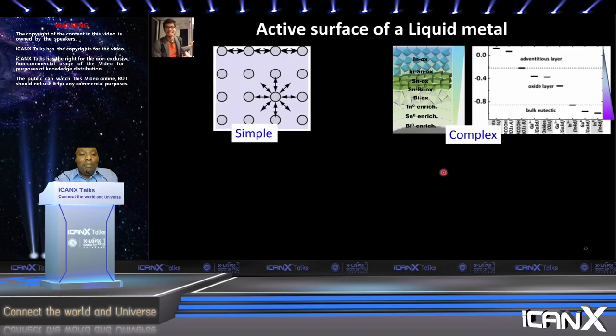And so we went back to our understanding of the surface of the liquid, and we know that by definition, a liquid will plastically deform to maintain the interatomic distance. But then that's for a simple liquid. What happens to a liquid like a liquid metal with an oxide sitting on it? You cannot have this kind of reorganization at the oxide shell. So the only place you can have that reorganization is where you have the liquid metal, which means that if I perturb the oxide shell, this metal will compensate and regenerate this equilibrium structure again, as we have seen with our fused metal and with EGaIn.